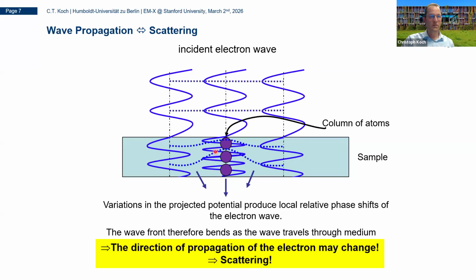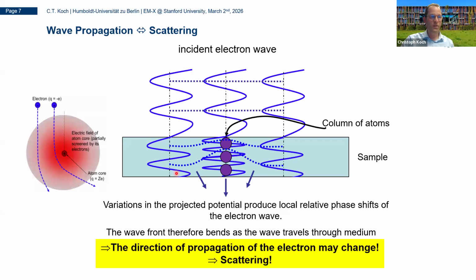So when you have a material, what actually happens is that this plane wave, so we assume there's a plane wave coming in, when it sees a column of atoms, it bends around. So the phase of this wave function is bent, which leads then to propagation, which is always, of course, normal to this wavefront, that you can compare to the scattering picture here by the potential of the atom. So both actually represent the same thing at the end. Here on the right-hand side is the wave picture, and here is more the scattering particle picture. We now mostly work in this wave picture because that helps us to do a number of things and also simplifies the simulation quite a bit.